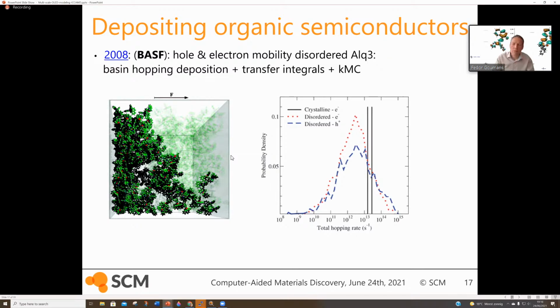So you can use it with force fields, but if you don't have an accurate enough force field, you can potentially run it also with electronic structure methods. So you could run it, for instance, with density functional tight binding. So here's an example of what that would look like. You need something that it could deposit on. In this case, we've chosen graphene, but it can be anything else. At some stage, it will fill up enough that you can freeze the bottom layers, and then it doesn't really matter anymore, and you probably throw away the graphene and the first deposition layer.